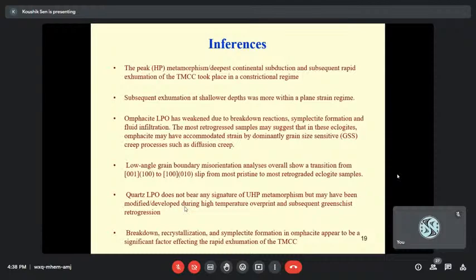Once diffusion creep comes into the picture, and zones of intense dislocation start getting healed, the strength of the LPO will weaken. A slight transition from the [001] axis and pole to (100) plane to [010] has been seen from most pristine to most retrograde eclogite. This is nothing new, nothing novel, because many studies have shown the same thing. What we were really expecting was some characteristic high pressure slip system, which we could not obtain from any of the samples. As I have discussed earlier, the quartz LPO does not bear any signature of eclogite facies metamorphism, but may have developed during HT overprint and greenschist retrogression.